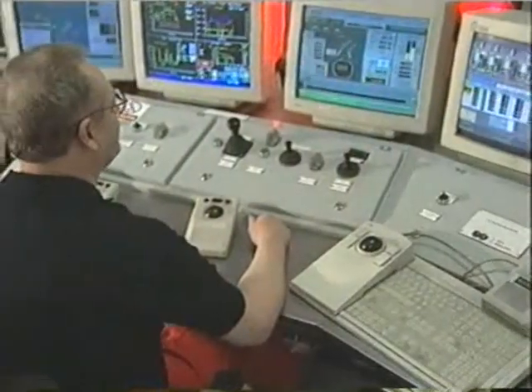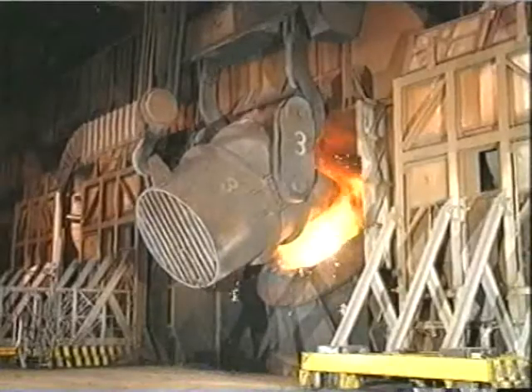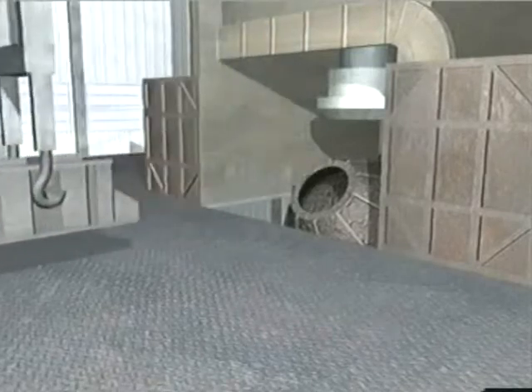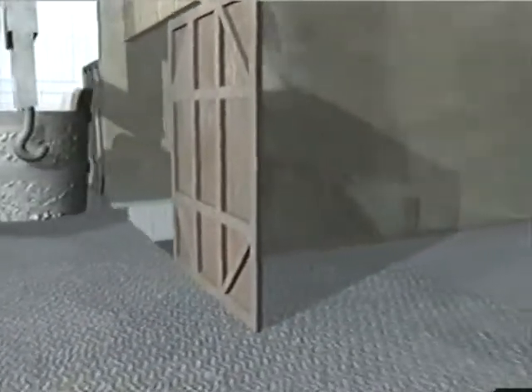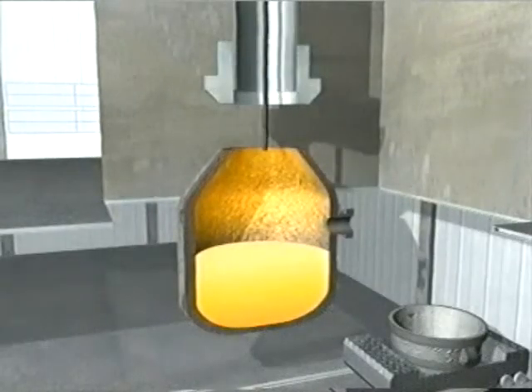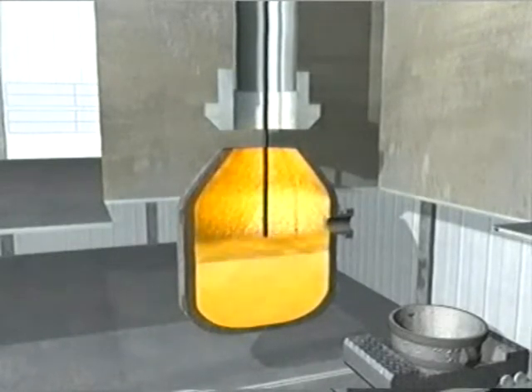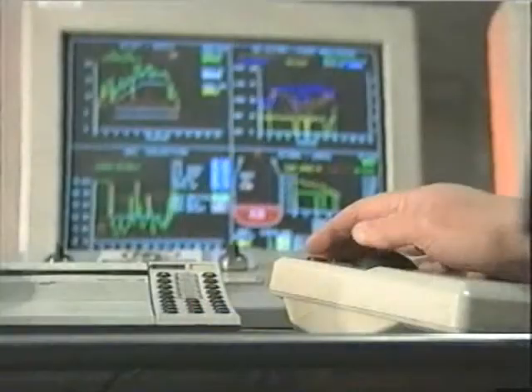Basic oxygen steelmaking, or BOS, is the main bulk production process for refining iron into steel. BOS vessels can take up to 350 tonnes of molten iron at a time, and convert it into steel in less than 30 minutes. First, scrap steel is put into the vessel, and then the hot metal is added, which may have been pre-treated to remove elements such as sulphur. A lance then blows high-purity oxygen onto the hot metal at about twice the speed of sound. The oxygen combines with impurities, and this oxidation produces heat. The temperature is controlled by the quantity of scrap steel, and also by the addition of iron ore as a coolant.